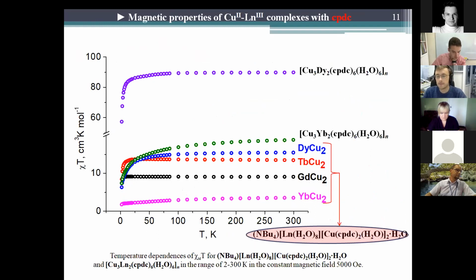And for the series of synthesized copper-lanthanide complexes, investigations of magnetic susceptibility were carried out in a static mode in a constant magnetic field. The values of chi T are constant up to 9 Kelvin and 20 Kelvin and 100 Kelvin for gadolinium, dysprosium, and terbium and ytterbium containing complexes.